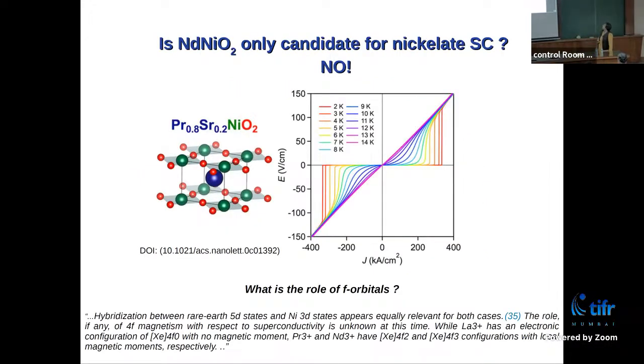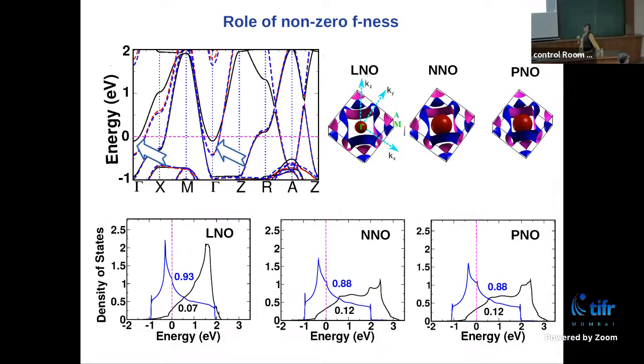So is neodymium nickelate the only candidate? The answer is no. Again, there was a paper from the same Stanford group where they found superconductivity in praseodymium with almost the same transition temperature as neodymium. Now, neodymium 3+ has 4f3, praseodymium 3+ is 4f2. So that means I'm changing the valence 4f electron, but apparently that is not doing much in the superconductivity. So the 4f possibly doesn't have much role in it. If it is so, in what way are they important?